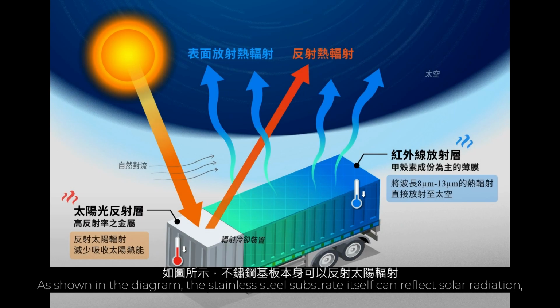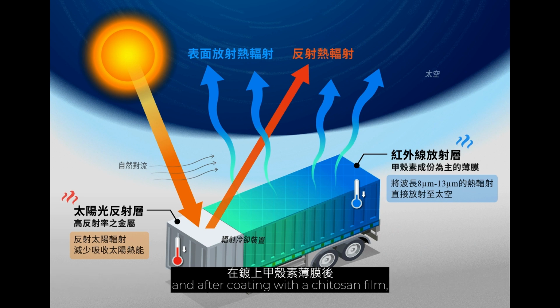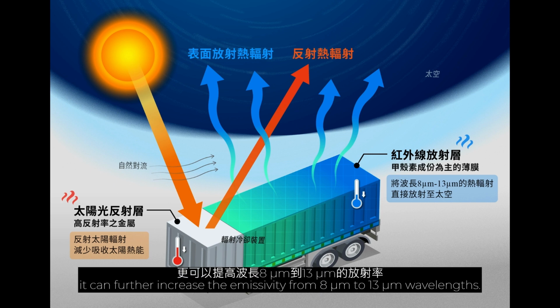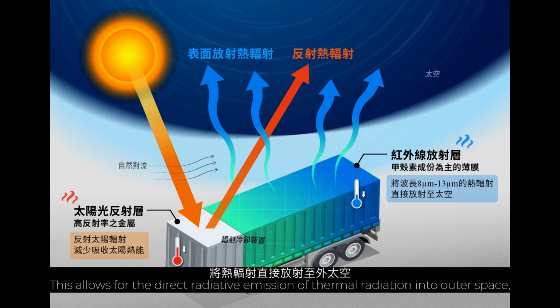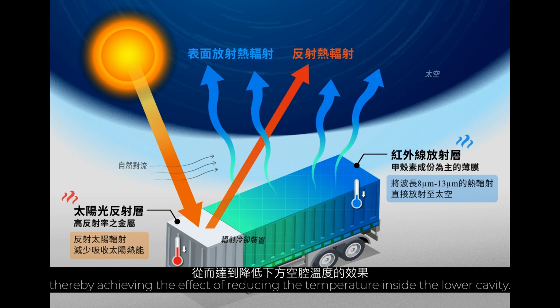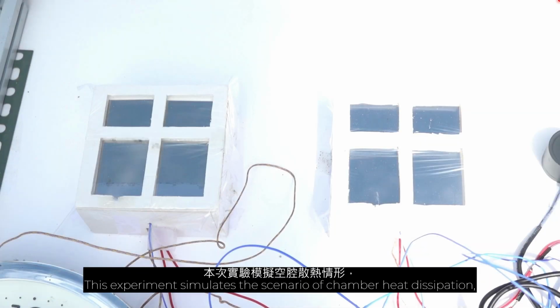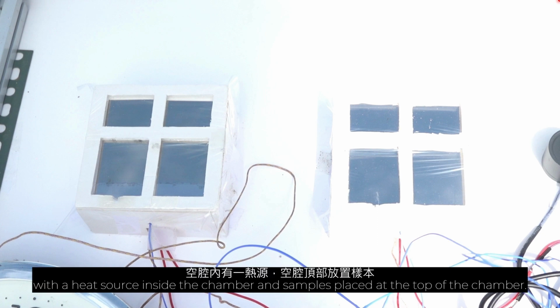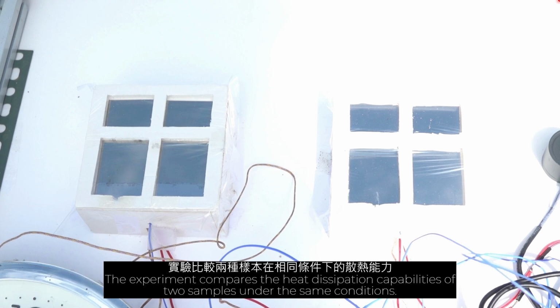As shown in the diagram, the stainless steel substrate itself can reflect solar radiation. And after coating with a chitosan film, it can further increase the emissivity from 8 micrometers to 13 micrometers wavelengths. This allows for the direct radiative emission of thermal radiation into outer space, thereby achieving the effect of reducing the temperature inside the lower cavity. This experiment simulates the scenario of chamber heat dissipation, with a heat source inside the chamber and samples placed at the top of the chamber. The experiment compares the heat dissipation capabilities of two samples under the same conditions.